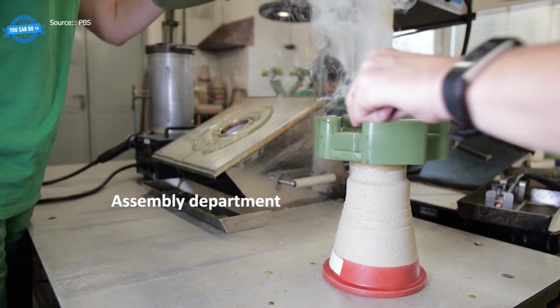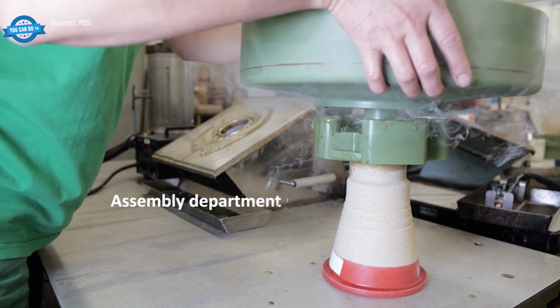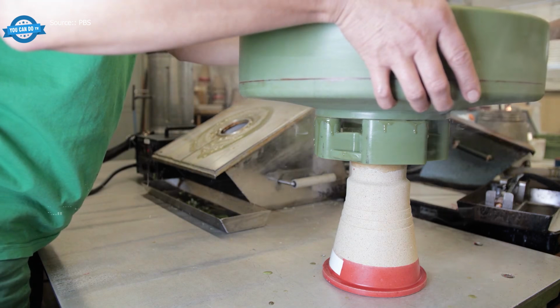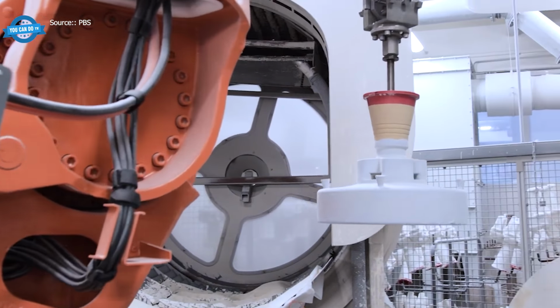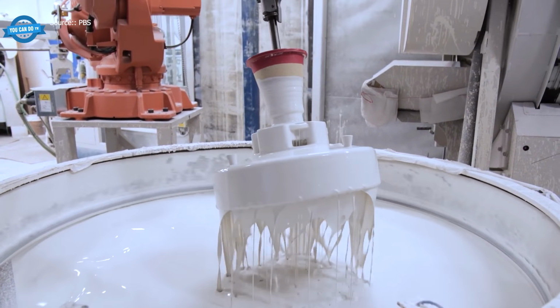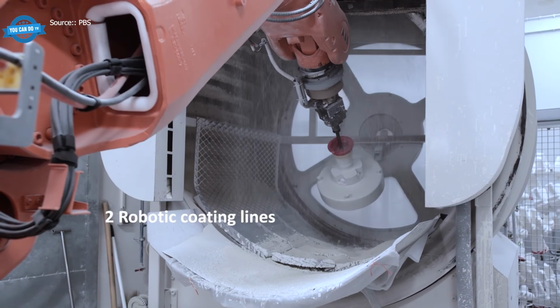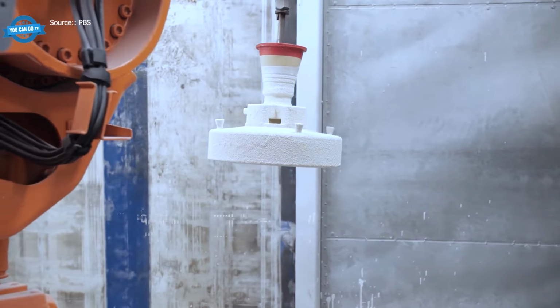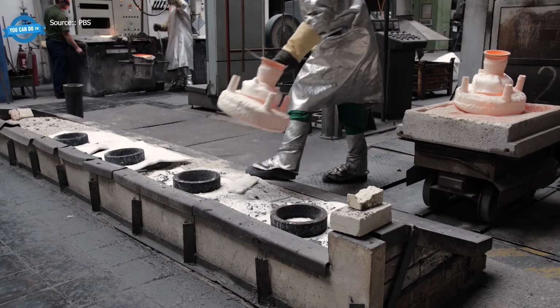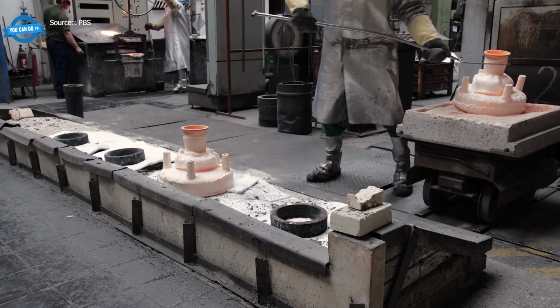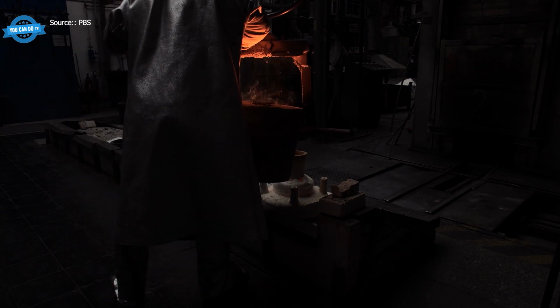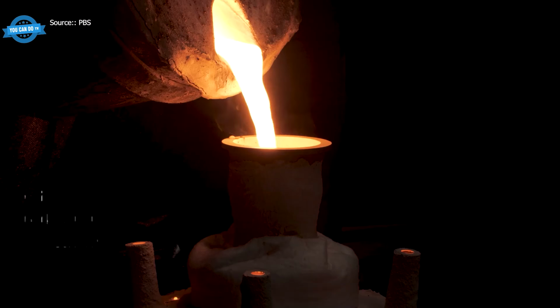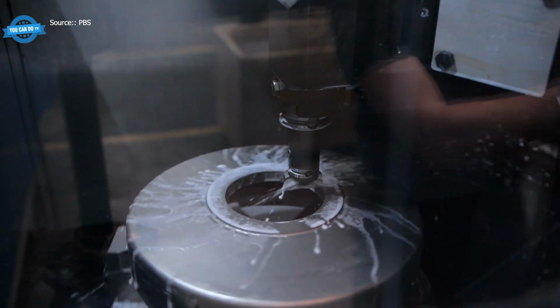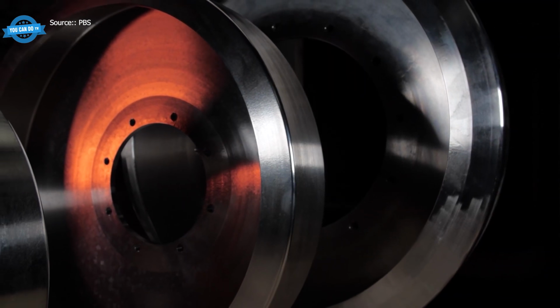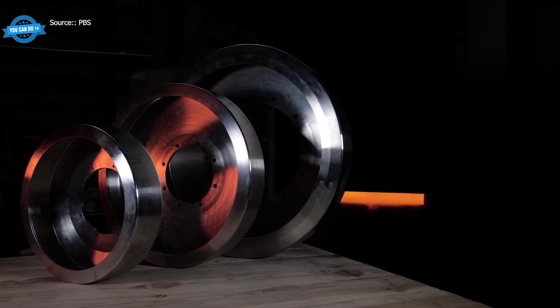Spinner discs are small in size but enormous in importance. These investment castings, made from nickel and cobalt superalloys, are what turn molten glass into the fine fibers used for insulation. The disc spins at high speed while molten glass is fed onto it, and centrifugal force throws the glass out through thousands of tiny holes on the rim. Every hole has to survive the heat.